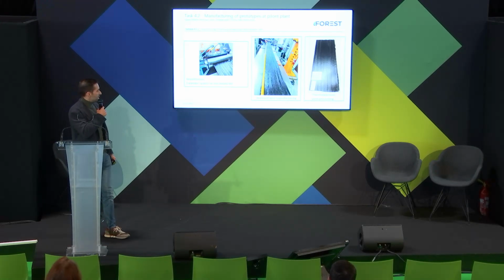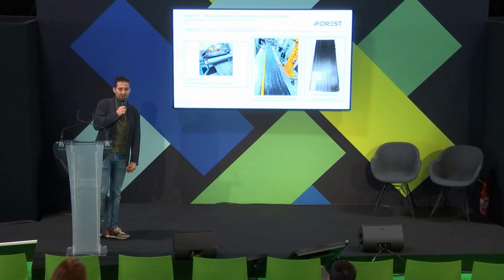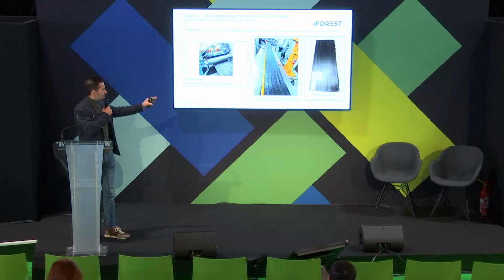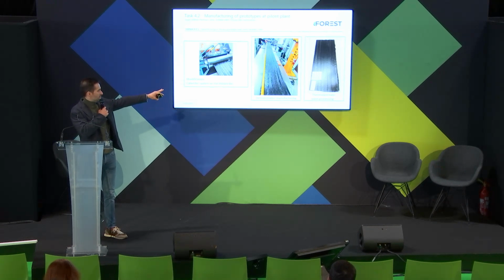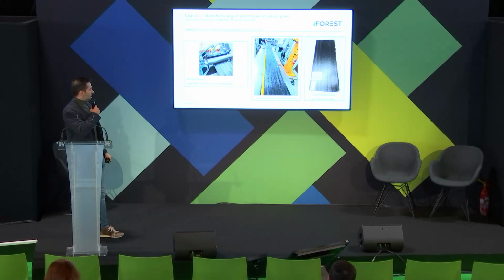And if we wanted to reach a better, smoother surface, we can post-process this in the thermolaminating equipment that I mentioned before. So this is in the end the profile, and you see that the surface is quite smoother and better looking.